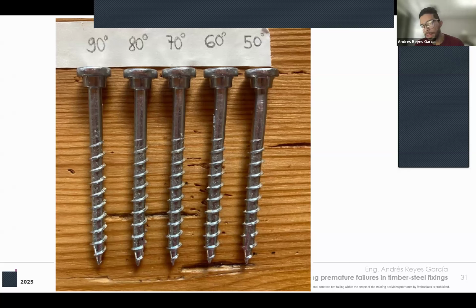the Eurocode 5 Part 3, has some recommendations specifically for fasteners and for the installation of fasteners in steel-to-wood or metal-to-wood connectors. They recommend more or less 5 degrees maximum. We find that's the only deviation that does not have a permanent effect. There is no plastic deformation, because 5 degrees is pretty much within the elastic range of the screws. But mostly because the elastic range is bigger than 5 degrees, it will not entail discontinuity on the coating, which is a very determining factor when we're talking about corrosion and then about hydrogen embrittlement.